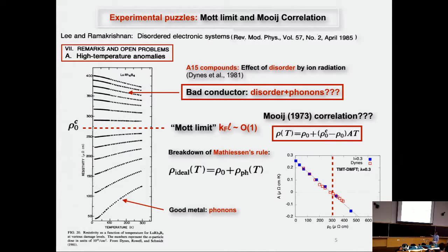And one of them was section number 7A, open problems, and high temperature anomalies was the first one on the list. What they pointed out was a classic experiment by Dynes, Rowell, and Schmidt in 1981, where they took a good metal. These are actually some of the A15 compounds, but as you will see, there are many more materials showing this. There's a metal, and if you go up to room temperatures, here's the linear resistivity. This is, of course, phonons. It's linear above the Debye temperature. At low temperature, it's a little bit different.